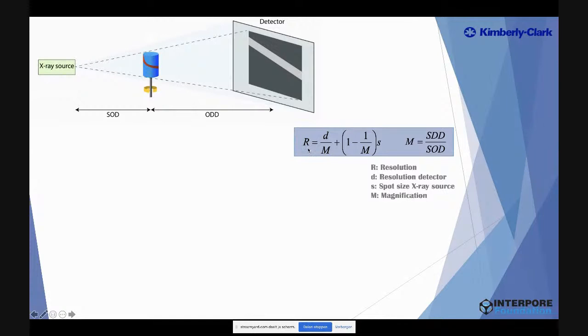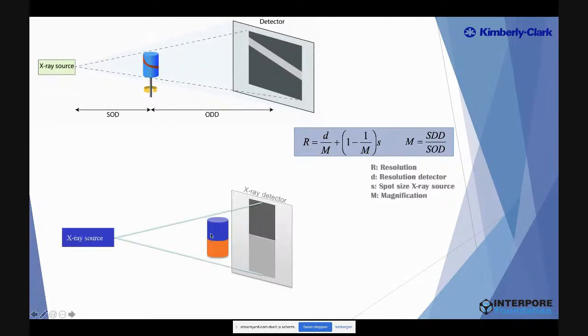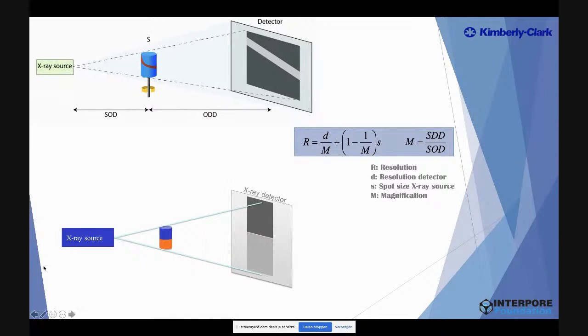So what is influencing the resolution? That is the spot size of your X-ray source, S, the resolution of your detector, and then the magnification. And the magnification of your system depends on the distance between your source and detector and the distance between your source and your object. So if you have a large sample that you want to scan, you will position it in such a way that during rotation, it remains in the field of view between your X-ray source and your detector. So you will position it rather far away from your X-ray source in order to visualize it completely. While if you have a small sample, you can put it closer to your X-ray source.